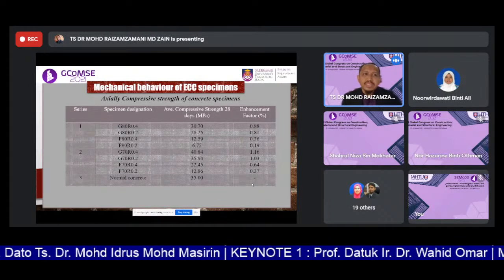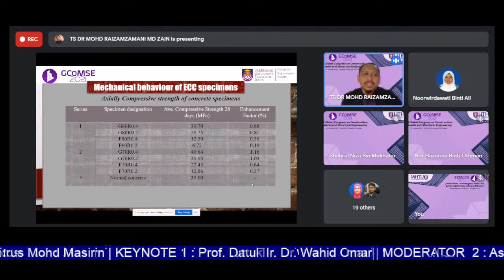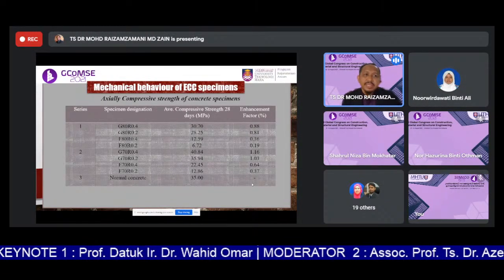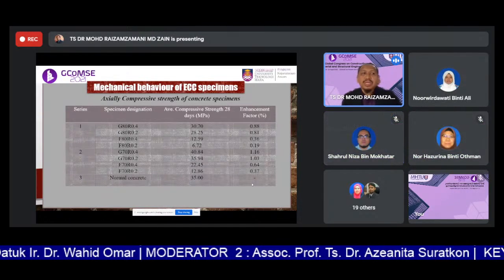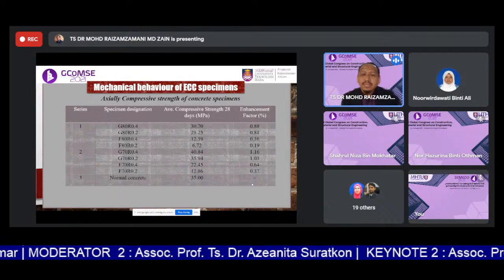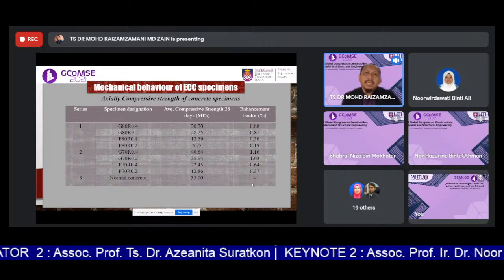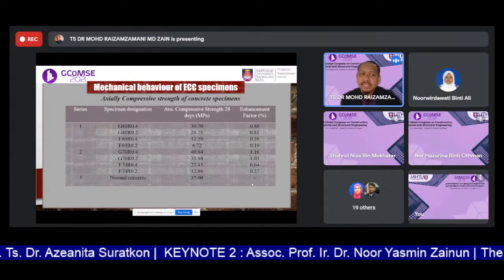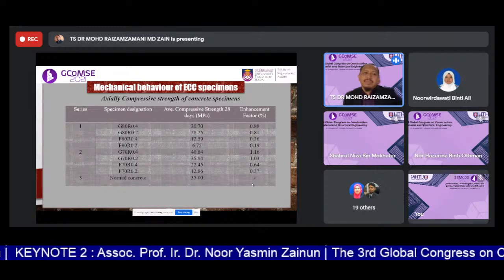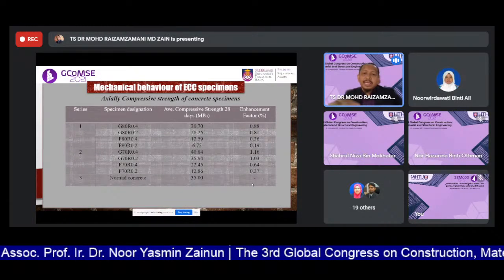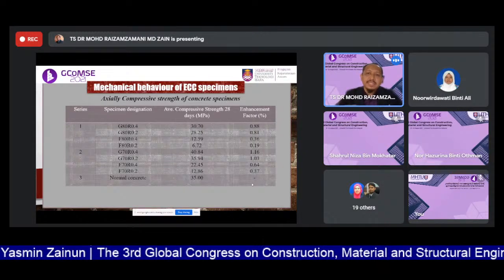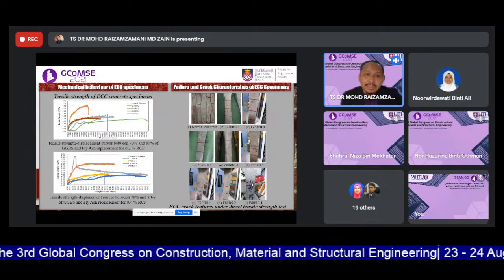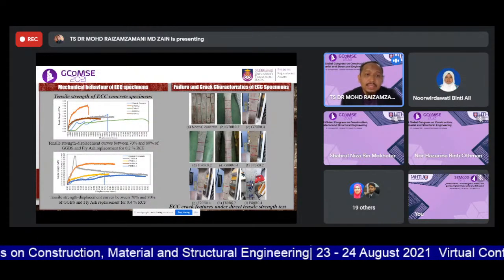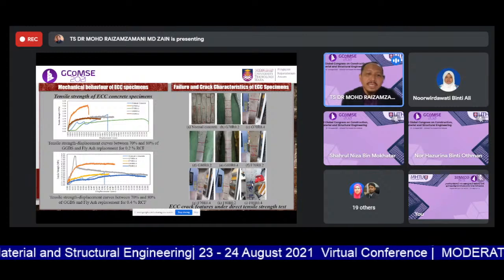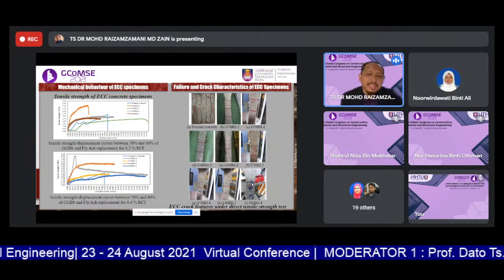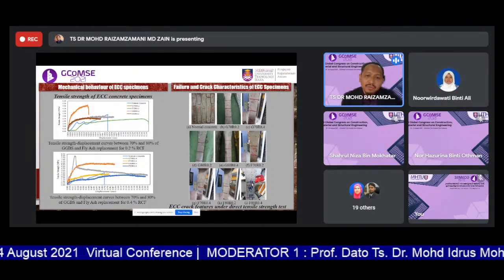The addition of GGBS to ECC concrete improves its mechanical properties. Because of the higher workability of the GGBS ECC mixture, it bonds well, improving the compressive strength. The action of the fibers also contributed to the higher compressive strength obtained by the ECC mixtures. So these are the outcomes for the compressive strength of the concrete specimens. Next, let's look at the direct tensile test. These 2 figures show the tensile strength displacement curves. The first figure indicates the curve between 70% and 80% of the GGBS and fly ash replacement for 0.2% RCF.